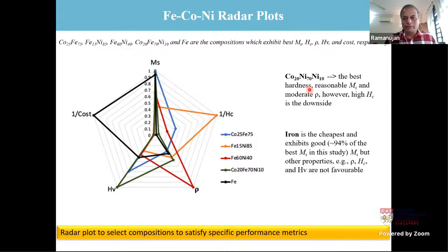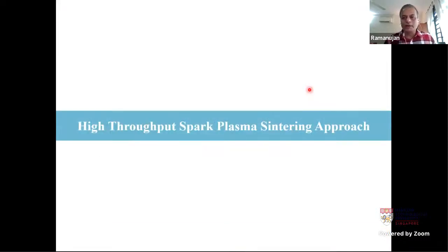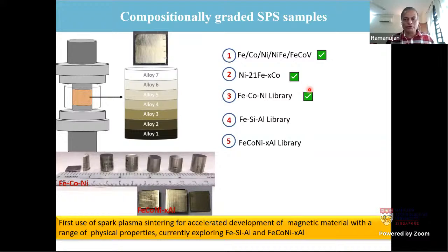Then we prepared samples using a different technique, which is making powders of different composition, stacking them up, and then using spark plasma sintering to produce a bulk compact. So in short, this is the schematic. Basically you take powders of different compositions and then use spark plasma sintering to produce bulk samples. But these bulk samples have, of course, graded composition. So in a way, you create a materials library. This materials library can be rapidly characterized and evaluated because it's basically a single sample.